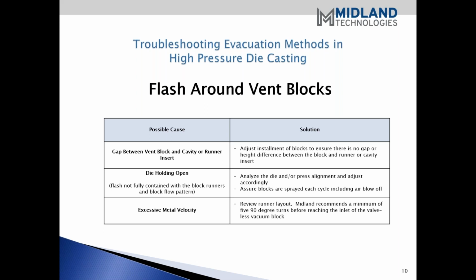Right. And then the third cause here is excessive metal velocity, and we kind of hit on this earlier, but what we see here at Midland is the runner layout. Again, the runner might have been designed where the metal is shooting into the chill block at a rate that's just too high velocity. And again, what we recommend is a minimum of five 90-degree turns on your runner outlet runners to the vacuum block, and that's what we see more effective once that's changed than perhaps some type of coating on the block. Would you agree with that, Larry?